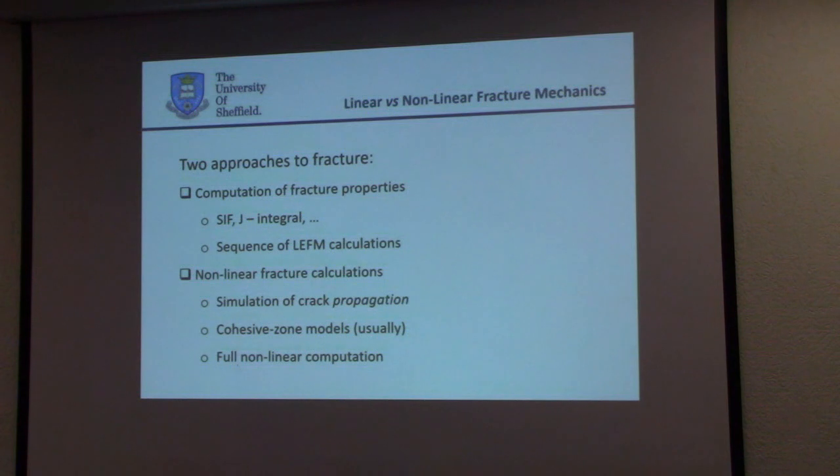If so, you propagate the crack by a certain amount, which usually is a bit of experience, and then you carry out a new calculation, usually a linear elastic calculation for this mesh. You compute new stress intensity factors or J integrals, and you propagate the crack, you make a new mesh, etc. Essentially, this is a series of linear elastic calculations.